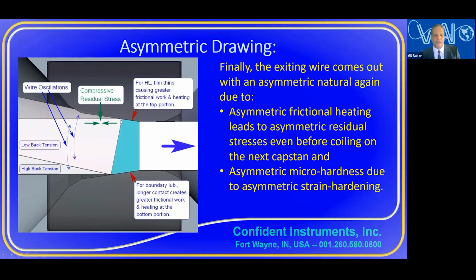So what's going to happen is, for example, it'll be hotter. The surface temperature will get hotter, again, especially with the hydrodynamic lubrication. And so that's going to cool down further and create greater tension here than here, where the wire surface was cooler. But the second thing is that when a particle of metal goes through this part of the deformation zone, you're going to have more strain hardening. So for micro hardness, you will have a harder material up here than you do down here. So two things make the wire exiting asymmetric.